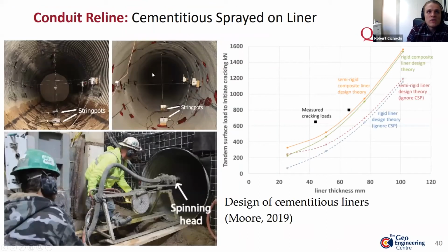One more technology that we looked at, and studied in our research facility as well and published literature about, is sprayed-on cementitious liners. Generally this method creates a concrete liner within the existing pipe. Typically the lining is pumped in at high velocities while a rotating head centrifugally casts the mortar onto the pipe. While the head spins, the machine runs back and forth through the pipe until the desired thickness is reached.